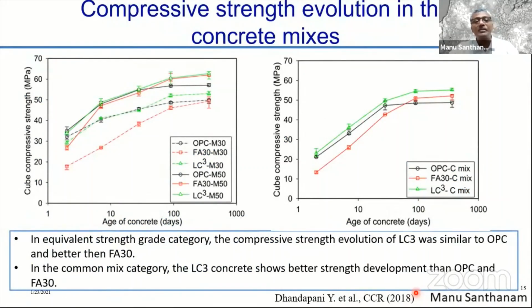If you look at compressive strength development as compared to 30% fly ash replaced cement and concrete, as well as ordinary Portland cement and concrete, there is not much difference in the strength performance. So you can actually produce good quality concrete with LC3, which is comparable to the best quality in ordinary Portland cement. And it is better than fly ash with respect to its early age strength development. In the long term, there is not much difference in the strength performance.